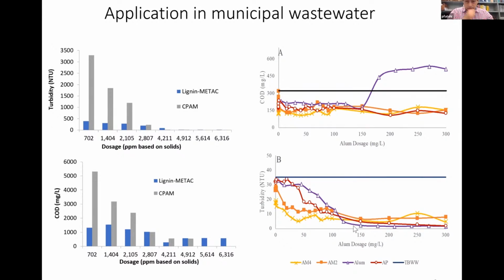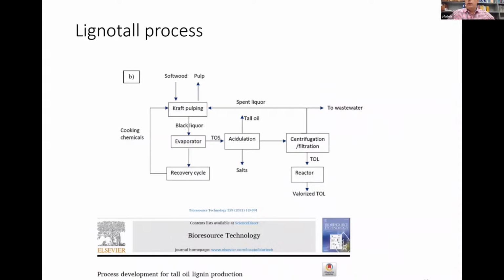So conclusion we had here was that if we use our polymer along with alum, we could reduce the alum dosage. For example, if you just use alum, you need 150 milligram per liter. If you use with their polymer, you still need a lot of alum. But if you use our polymer, this point is better. So around 50 milligram per liter. So we could reduce the alum dosage by 60%, 70%. So that's huge, because then again, consider the problem of sludge handling and sludge dewatering and landfilling and so on.